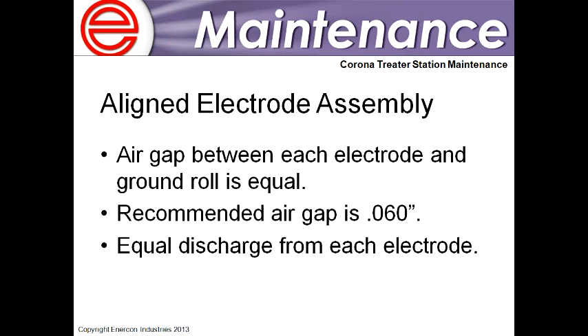Yep, so now we're aware of some of the problems that can arise, what we want to do is measure the air gap between the electrode and the ground roll on each side of the electrode, and we'll go through that in the next slide. The other thing is the air gap that we recommend is 60 thousandths of an inch, 1.5 millimeter. And it's not necessarily a magical number. It's just what we found is 60 thousandths is wide enough to allow a majority of materials and applications to pass through the treater without any physical impact, and yet also narrow enough that we're not putting any undue stress on the high voltage wires, the electrodes, the insulating shroud, that type of thing.